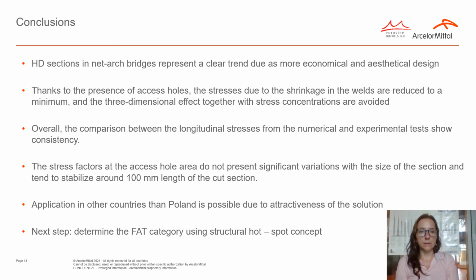So to conclude, HD sections in net arch bridges represent a clear trend as a more economical and aesthetic design is required. Thanks to the presence of the access hole, the stresses due to the shrinkage in the weld are reduced to a minimum, and three-dimensional effects together with stress concentration are avoided. Overall, the comparison between the longitudinal stresses from numerical and experimental tests shows good consistency. The stress factors at the access hole area do not present significant variations with the size of the section and tend to stabilize around 100 mm length of the cut section.